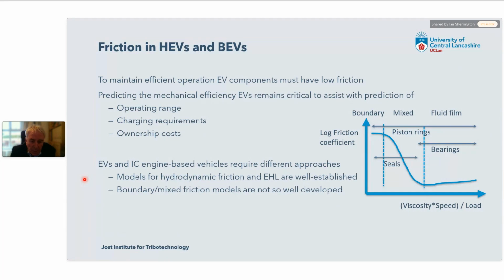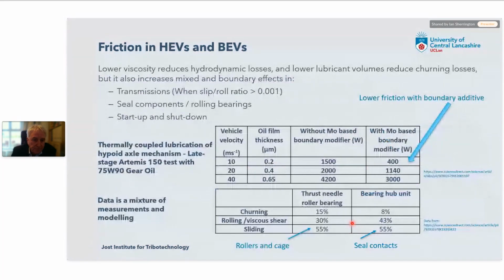So hydrodynamic models and EHL models are well established, and running alongside that, boundary mixed friction modeling is not so well established. And what we find in this instance is that these models are quite often, as I mentioned earlier, very simple but not very accurate, or complex and difficult to implement. And what we want to do with these models is to try and understand the Stribeck curve, try and predict the shape of the Stribeck curve, so that we can use data that we can easily get our hands on, either these duty parameters or the lambda ratio, and understand what kind of friction may result from one of these contacts. Why is that important?